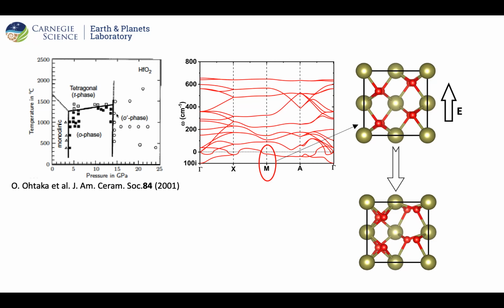And if you do a group-subgroup relationship analysis of the PBCN phase, from the M point, you combine it with a gamma 2 plus, you get the monoclinic. From the M point, you combine it with the gamma 5 minus, you get the PCA2 sub 1 phase. And even for the tetragonal, if you focus just on the gamma zone center phonon, you can also get the other polar PMN2 sub 1 if you freeze in the gamma 5 minus soft phonon. So if, let's say, you start at tetragonal, freezing the M distortion, you get the PBCN. Now, if you apply an electric field, then you drive it to the PCA2 sub 1 phase.